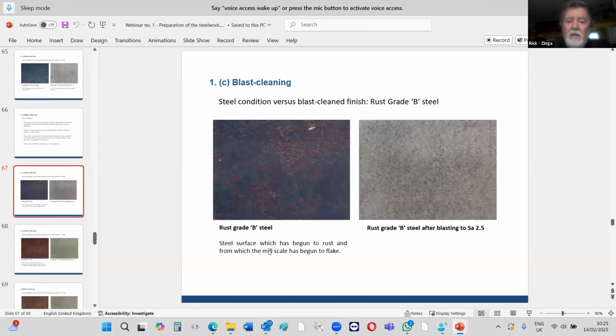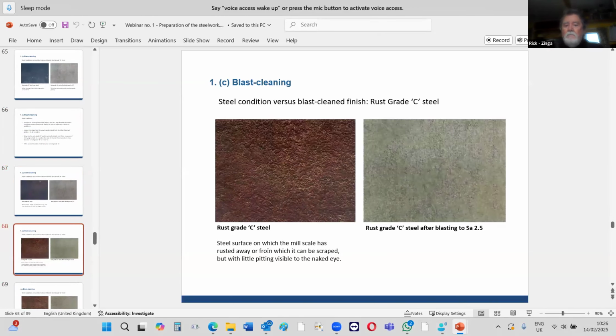So this is a rust grade B. You can see it's got some pitting on the surface because it's been lying around a while. But after blast cleaning, it looks okay. That's perfect for Zinga. Absolutely perfect. Rust grade C, that's been lying around a lot longer. And you can see that on the left-hand side, the corrosion is much deeper. But once again, after blast cleaning, and this is using copper slag, still looks perfect for Zinga.